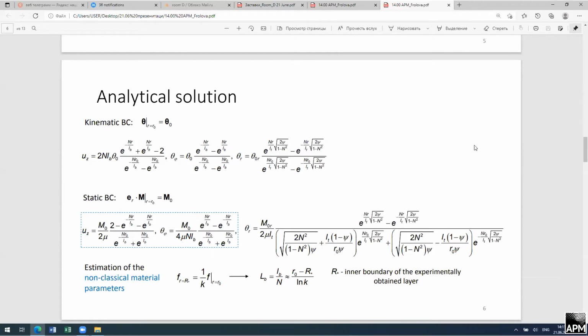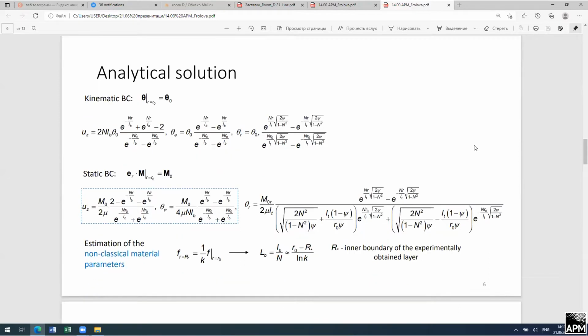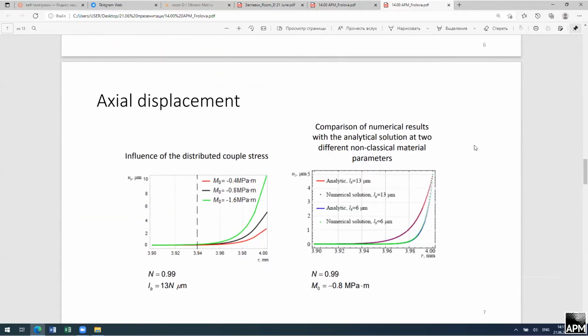To estimate non-classical material parameters that are not known from experiments, we assume that solution decreases by a factor of k at the inner boundary of the experimentally known layer in comparison with corresponding values directly on the border. And here we analyze axial displacements. On the left plot, you can see analytical solution for axial displacement. And we can see that the value of the distributed couple stresses affect the value of the axial displacement, but it doesn't affect the thickness of the boundary layer.